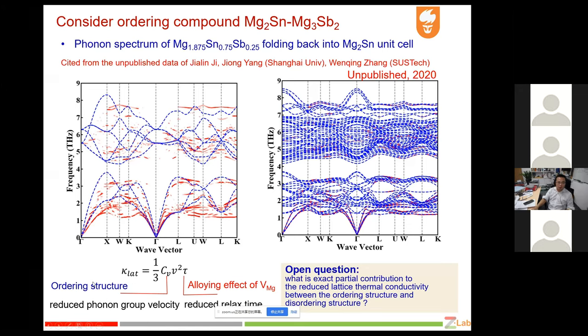However, this spectrum calculation shows that the ordered structure can also contribute to the reduced lattice thermal conductivity. Now we also have an open question: what is the exact partial contribution to this reduced lattice thermal conductivity between the ordered structure and the disordered structure?